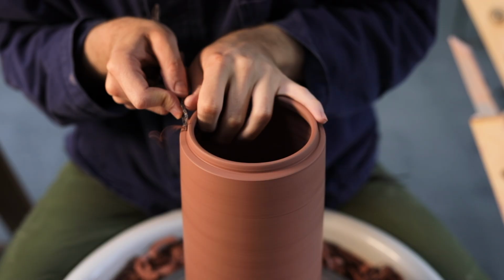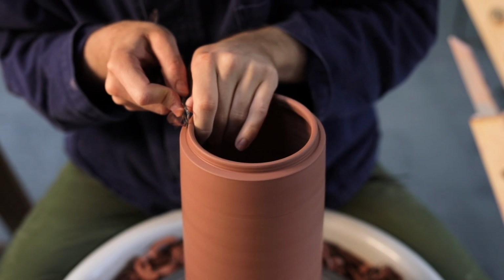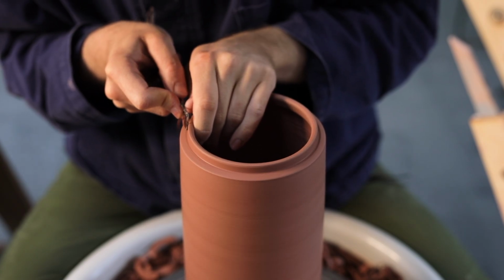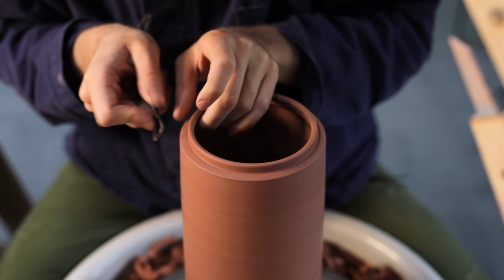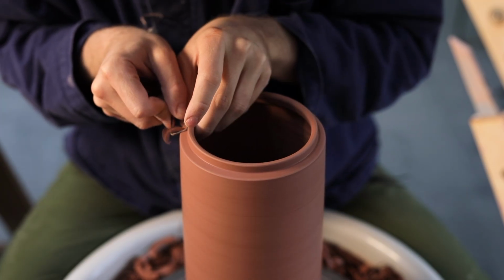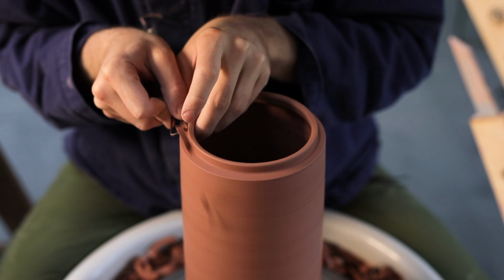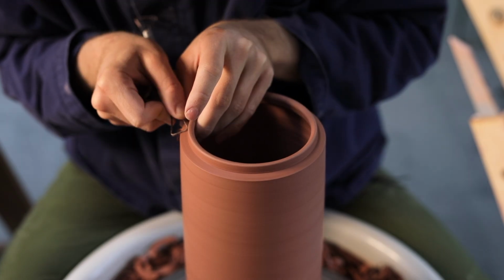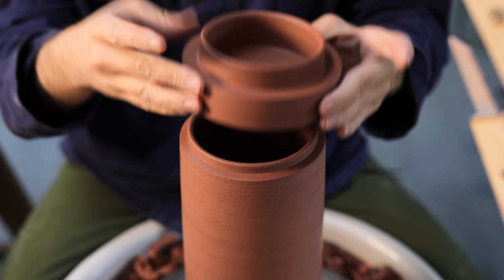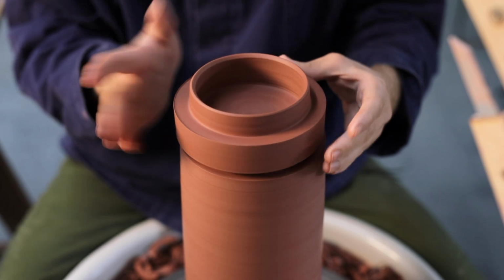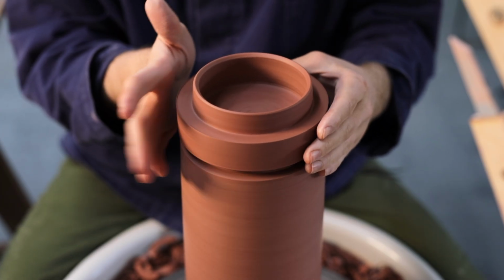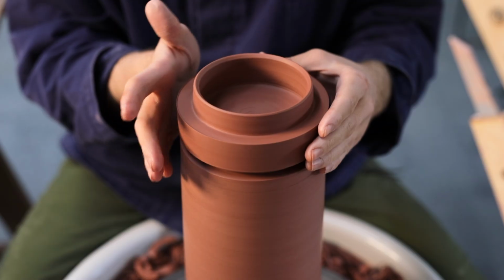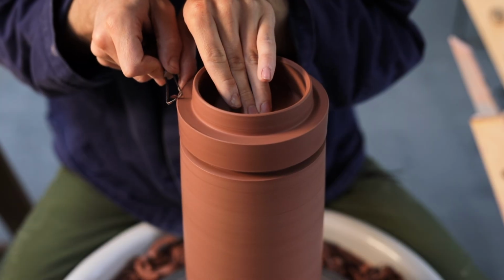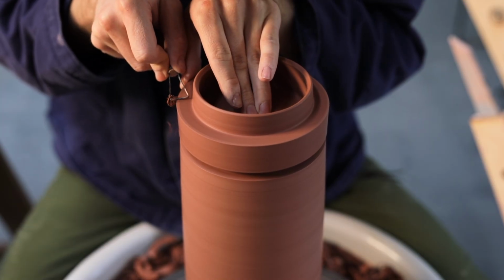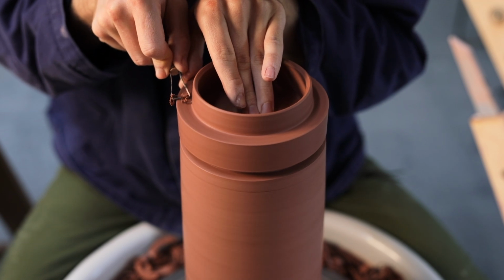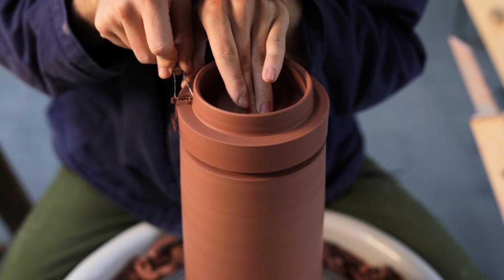Once the lid has been trimmed, I then remove it and turn the gallery underneath. And this is something I always do secondary to turning the lid, as once or twice when I've turned the gallery first and then trimmed the lid, the pressure of pushing the lid down into place has caused the gallery itself to crack, rendering the whole pot useless and destined for the reclaim bucket. I then usually flip the lid quickly upside down and just neaten up this outer edge, which usually just gets a bit scratched and marked throughout this process.